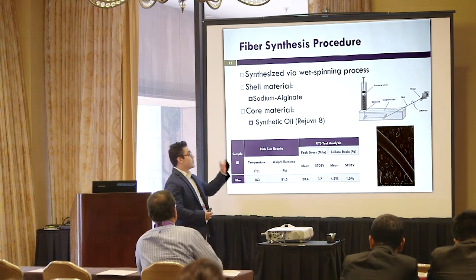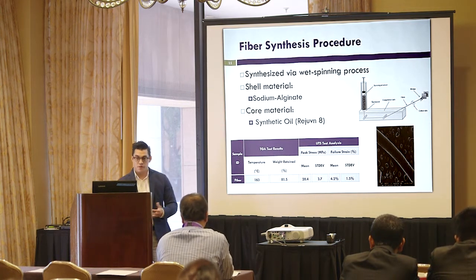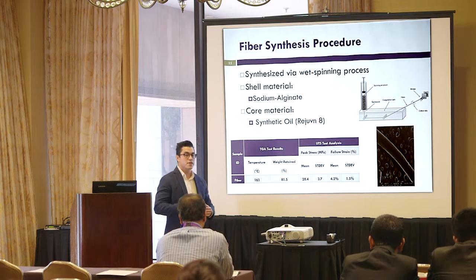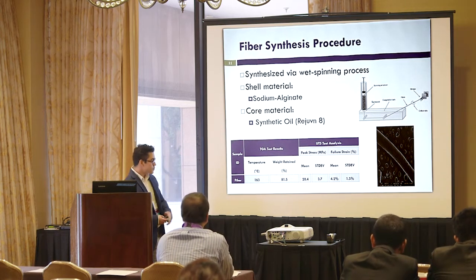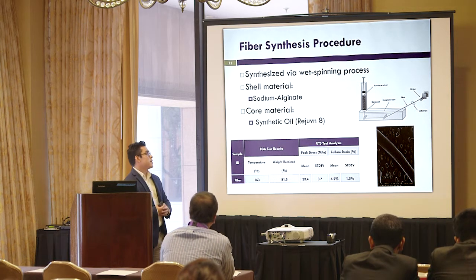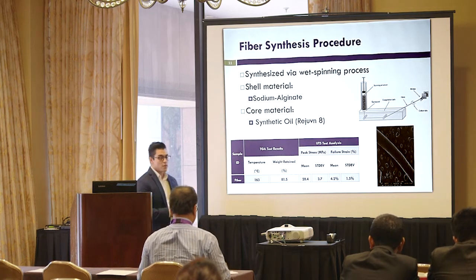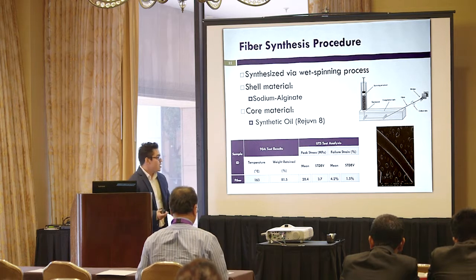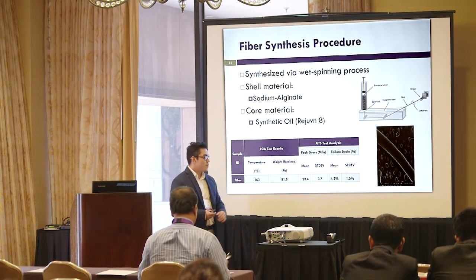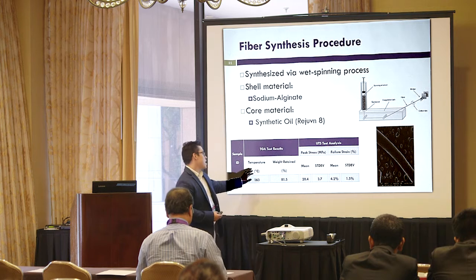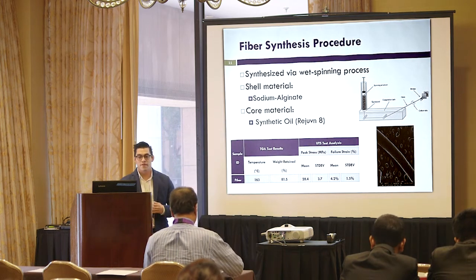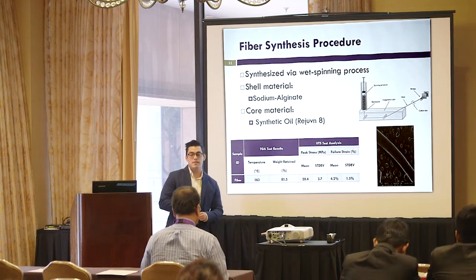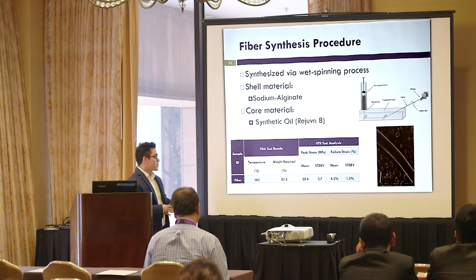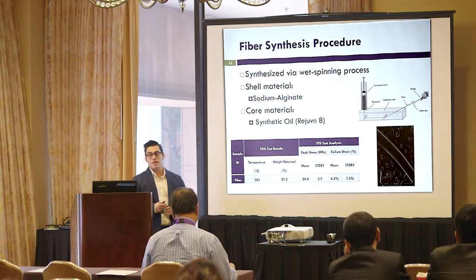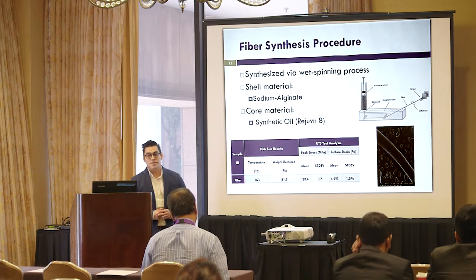As I mentioned before, for the shell material we use sodium alginate because of its biodegradability properties. And the type of rejuvenator that we are encapsulating is a commercial product called Rejuvn 8. So that's a scanning electron microscope image of the fibers. And we also performed a thermogravimetric analysis and some tensile tests in order to make sure the fibers were not going to get destroyed during the mixing process.